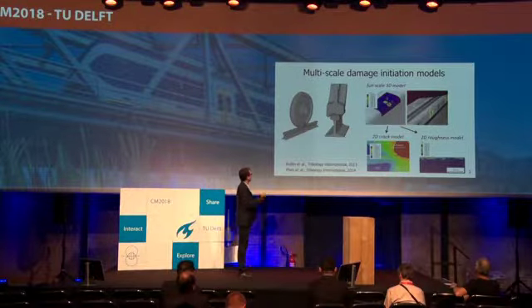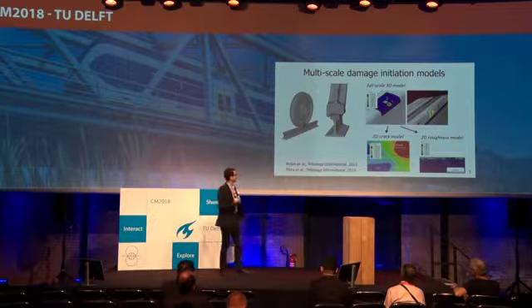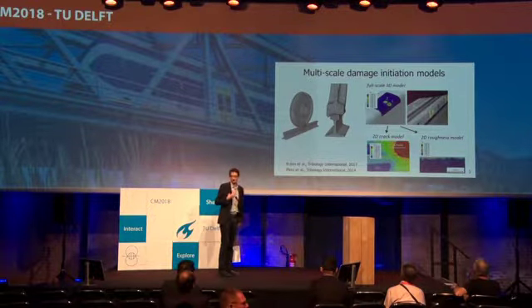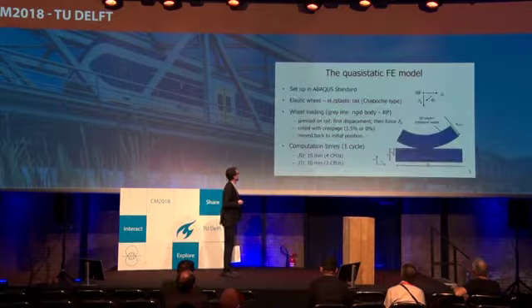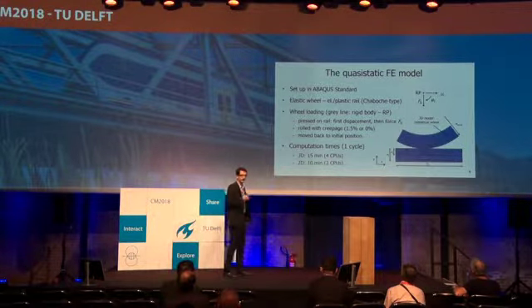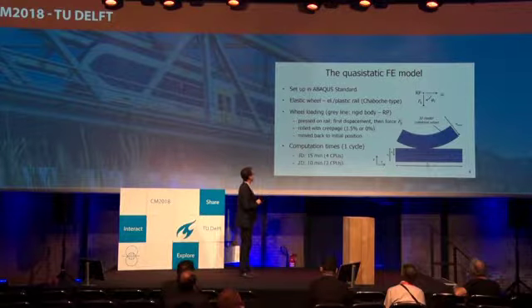Well, one thing there was we just showed how it could be done, but we didn't really show how it was feasibly done. So now I introduce a quasi-static finite element model where we do something like that, but it's a little bit more basic. We have an elastic wheel because we're not too much interested in the wheel, but we have an elastic plastic rail at that point with a Chaboche type cyclic hardening model.